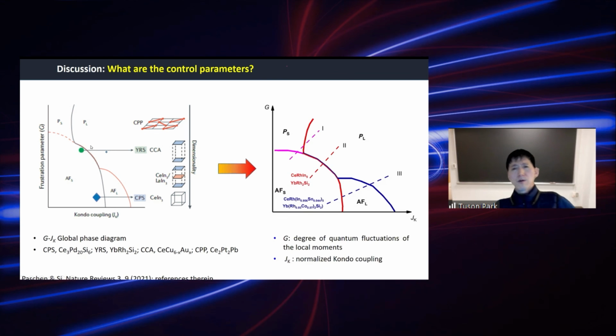So I think we can naively think that ytterbium rhodium 2 silicon 2, which is the candidate for a quantum breakdown quantum critical point, the pure compound tracks from here, this number 2 line, from F small to paramagnetic large Fermi surface. On the other hand, when you dope tin into cerium rhodium 5, then it becomes less frustrated, or the degree of quantum fluctuations of the local cerium 4f moment is smaller. That's why it has to go through the AF small, the AF large, and then the paramagnetic large Fermi surface phase,